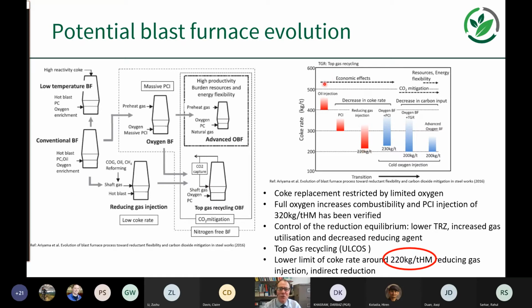And then on the right hand side, we've got a figure that illustrates the reduction in this coke rate, which is very important. Of course, there's a theoretical minimum for that, because of this requirement for the gas permeability. But some significant improvements in the coke rates associated with the blast furnace there.